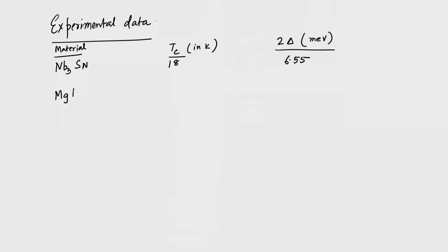This is a fairly newer superconductor, a boride superconductor, called magnesium boride. It has a Tc of 40 Kelvin, and 2 delta equal to 10 meV. Then Rb3C60, these are the intercalated organic superconductors, which has a Tc of 30 Kelvin, and the gap is about 12 meV, and there is an erbium rhodium boron compound that has a Tc of 9 Kelvin, and this is equal to 3 meV. So, as you see, there is a nice correlation, or rather 2 delta very closely correlates with Tc. So, once you have the magnitude of the gap available through experiments, an estimation of the Tc is also available.